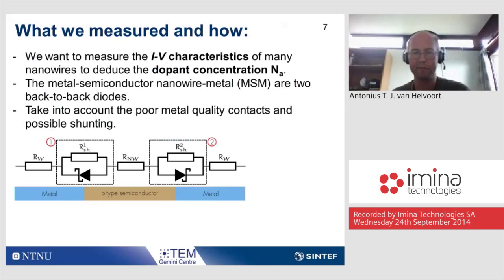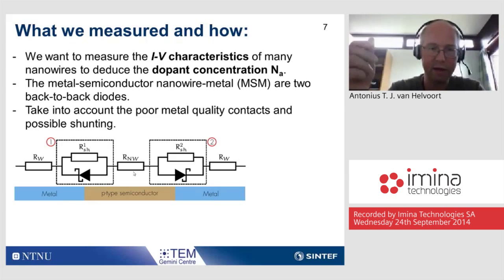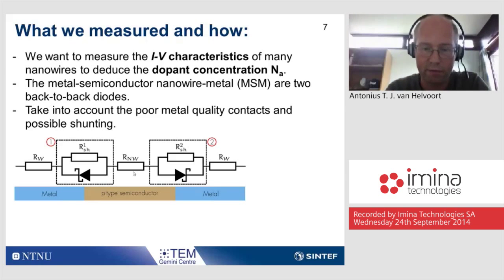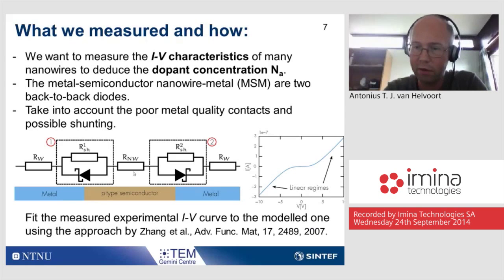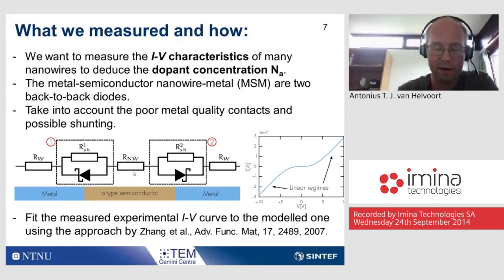So in this case, schematically shown here, we have the brown nanowire, and on both sides we have a platina metal contact. So in the middle we have the resistivity of the nanowire, on both sides we have the resistivity of the deposit we made, and then the actual Schottky contact is like a diode, and there is possibly a shunting over it. If we now measure the IV curve, it's such a curly shape with linear parts and exponentially decaying parts. By taking some assumptions, you have to see the reference there, we can deduce the dopant concentration.